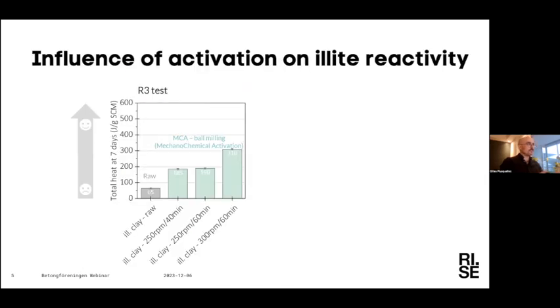So we wanted to see what we can do to activate this type of clay. I'll show some results of the R3 test only on illitic clays. I won't talk more about this test because Ruben detailed it in his presentation. Here on the graph, I present the total heat at 7 days for different materials. In gray is the illitic clay without any treatment. The different green bars are the reactivity of the clay after mechanochemical activation, or MCA, made in this case by ball milling. Depending on which parameters we use, we have quite an impact on the reactivity, so it's important to take care of the actual parameters you use for such activation. But we can also see that with the proper parameters, you can have a reactivity that is actually quite good.